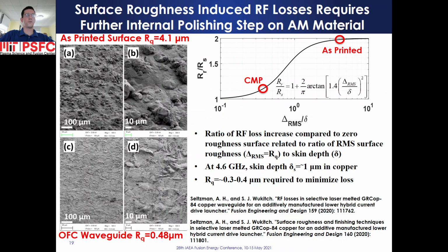Surface roughness-induced RF losses require internal polishing of additively manufactured material. The ratio of RF loss increase on a rough surface compared to an ideal perfectly smooth surface is related to the ratio of RMS surface roughness to RF skin depth in the material, as plotted on the right. At 4.6 GHz, the skin depth in copper is 1 micron, requiring an RMS roughness of 0.3 to 0.4 microns